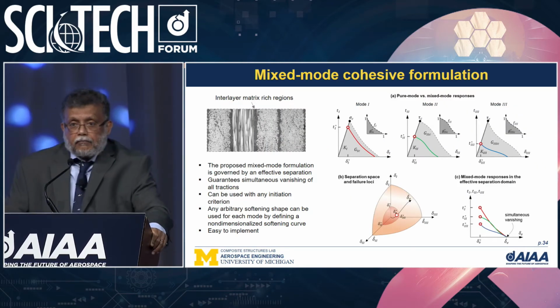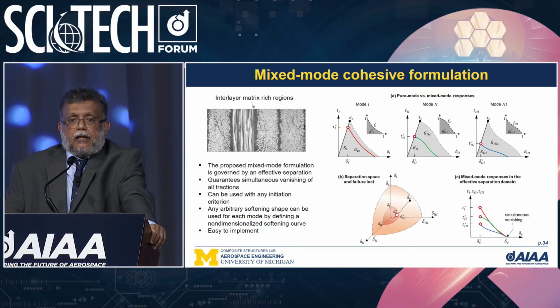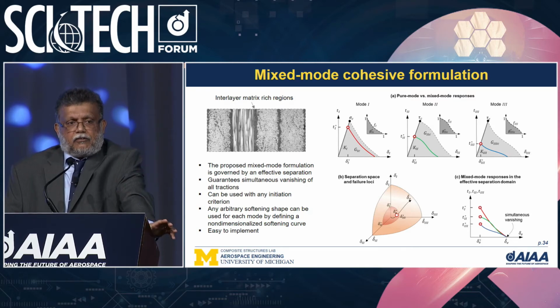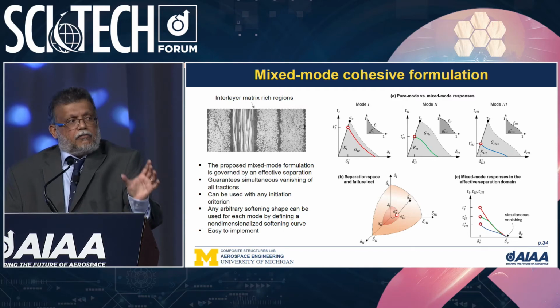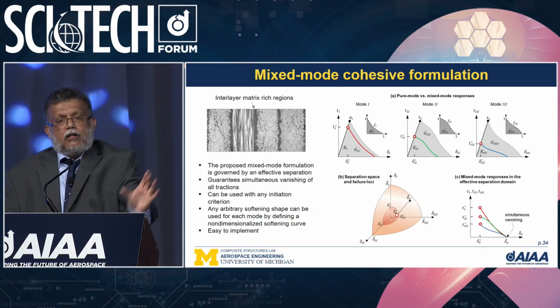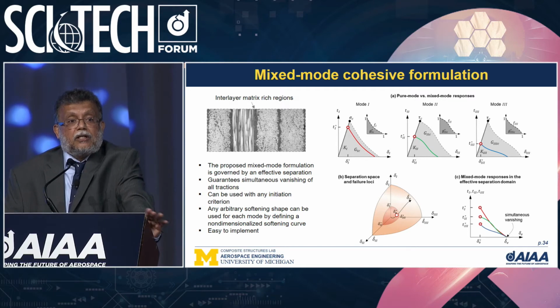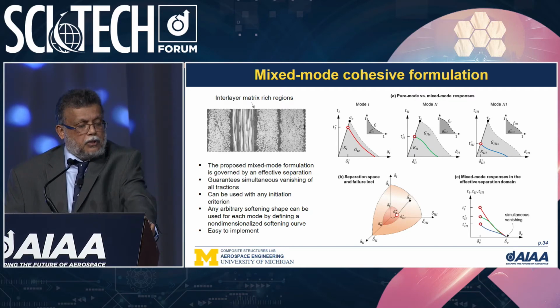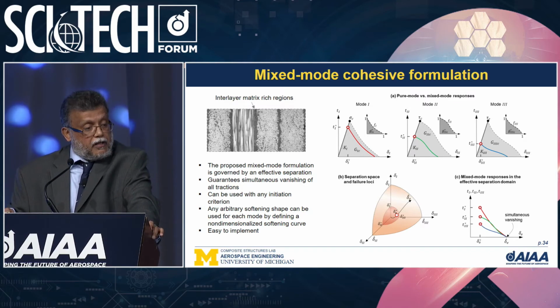Most of the damage modes are mixed mode, meaning damage is not occurring because the state of stress is uniaxial. In fact, most of the time these damage modes occur in a multi-axial stress state, which means you must have a good mixed mode formulation to get correct results. One key is that when a damage zone passes a point, all the tractions in the cohesive law must vanish simultaneously, and that's assured with this new mixed mode formulation we have adopted.